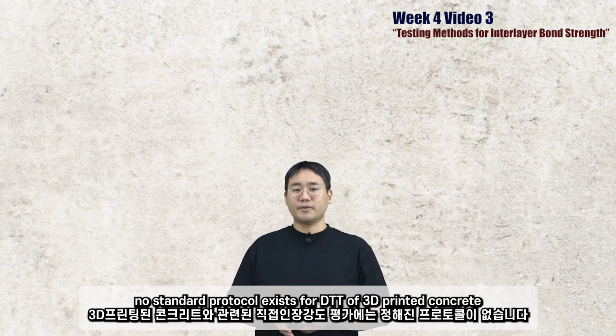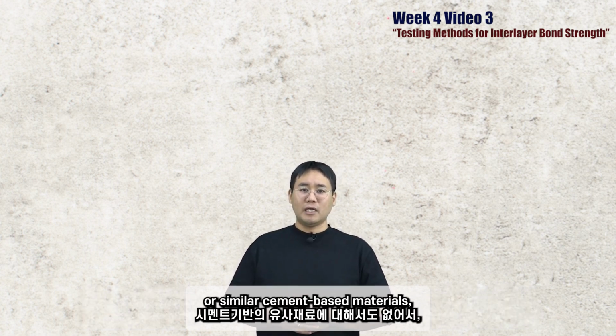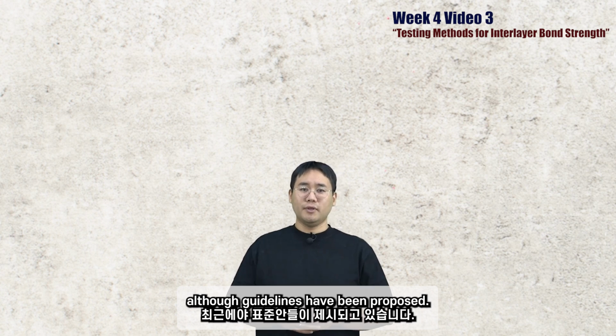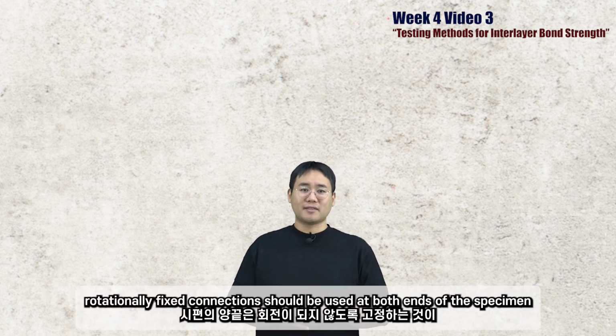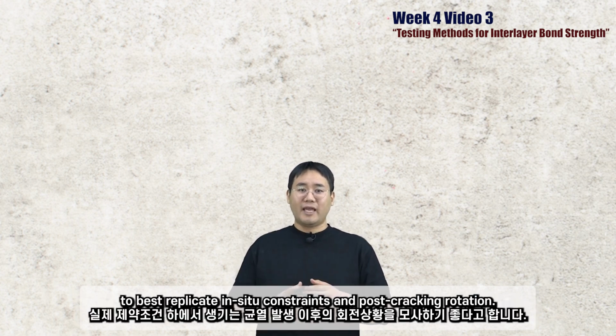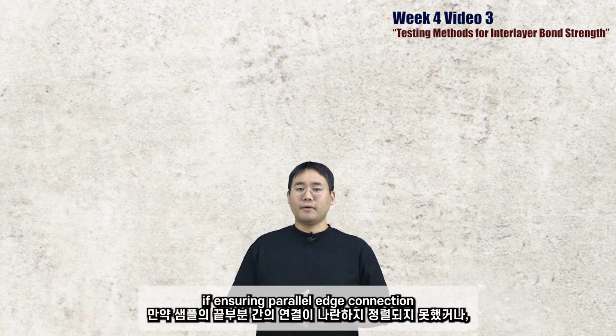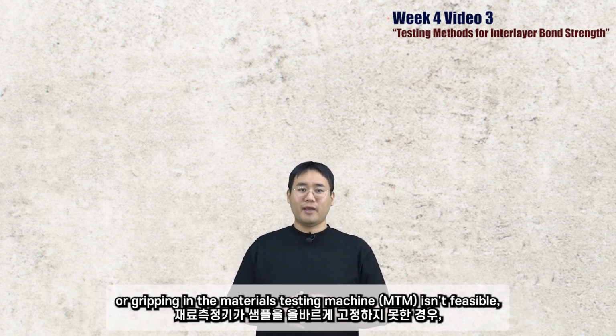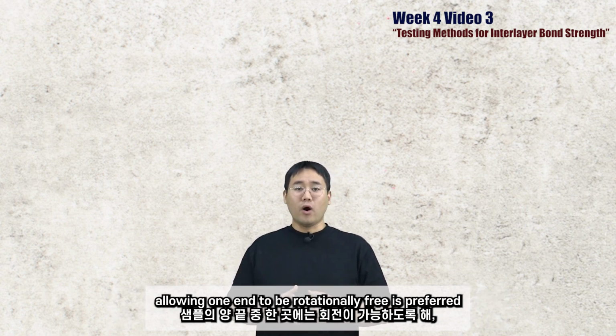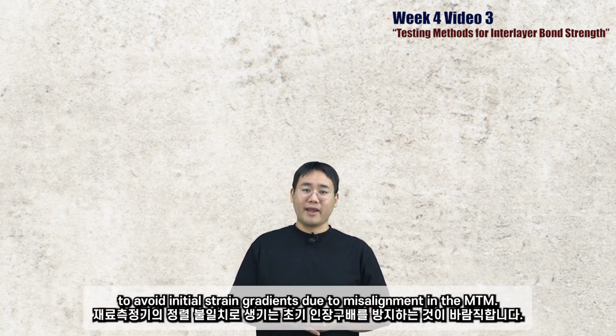Currently, no standard protocols exist for direct tensile tests of 3D printed concrete or similar cement-based materials, although guidelines have been proposed. There's a consensus that rotationally fixed connections should be used at both ends of the specimen to best replicate in situ constraints and post-cracking rotation. However, if ensuring parallel edge connection or gripping in the materials testing machine, or MTM, isn't feasible, allowing one end to be rotationally free is preferred to avoid initial strain gradients due to misalignments in the MTM.